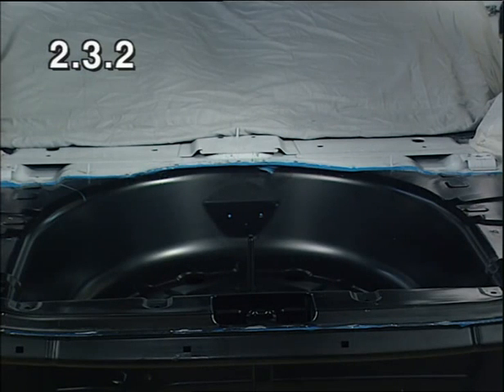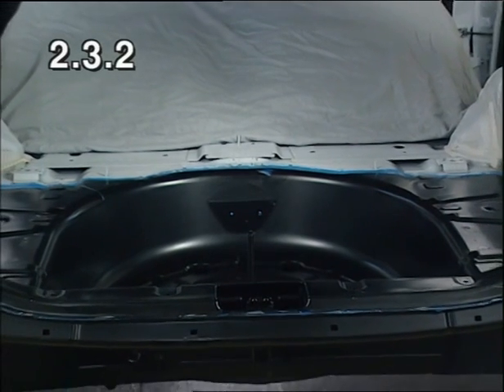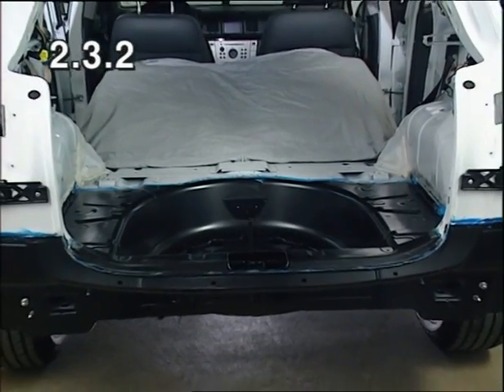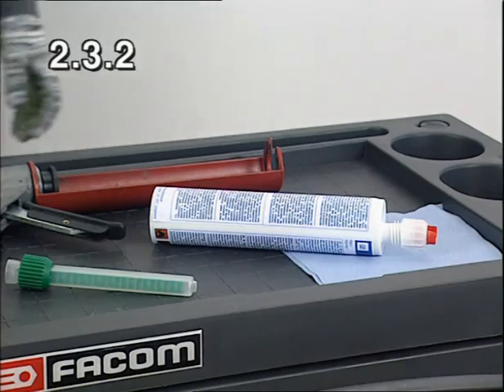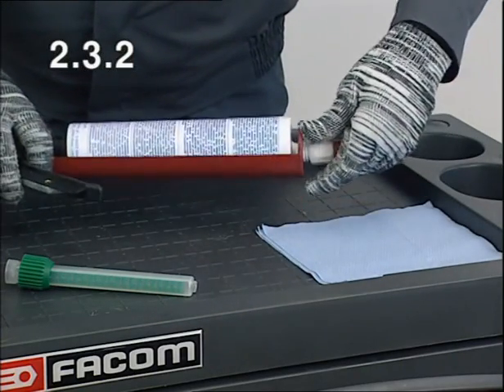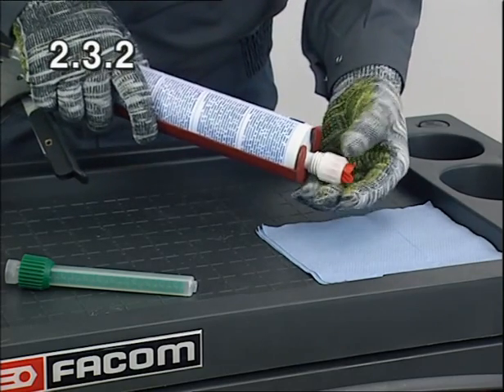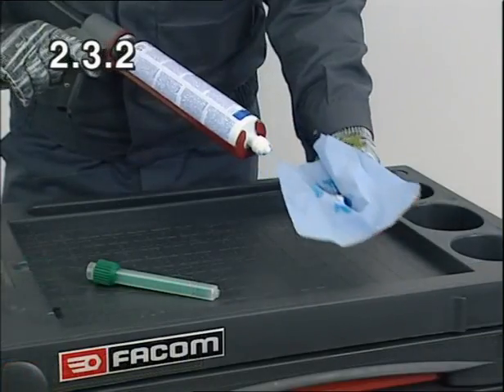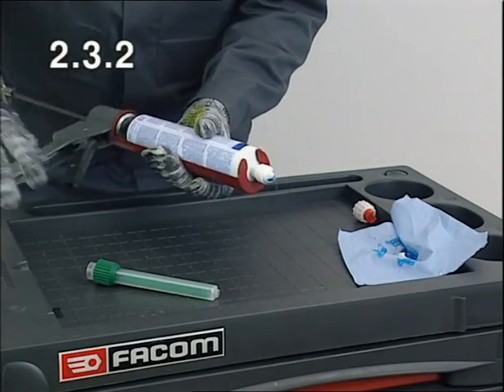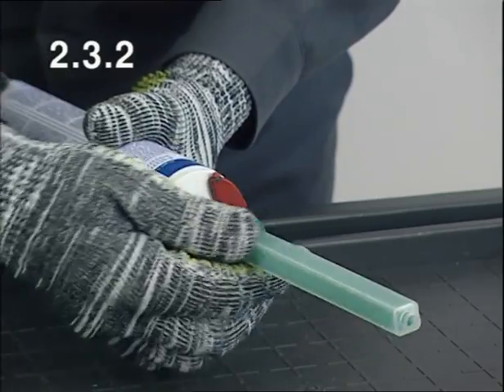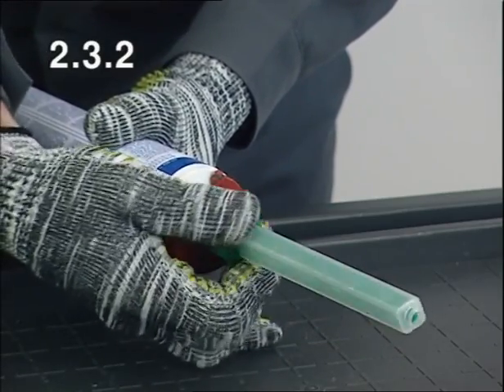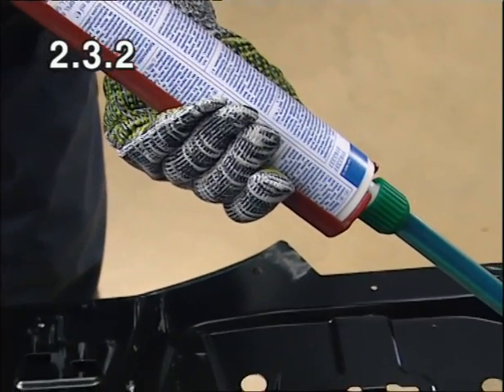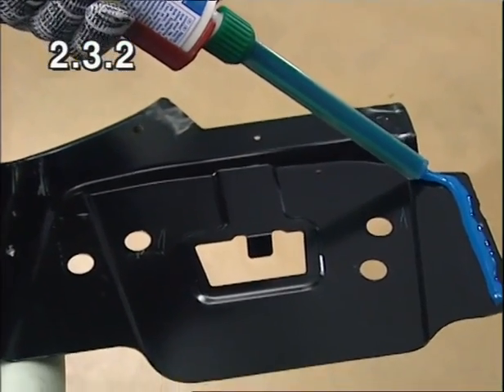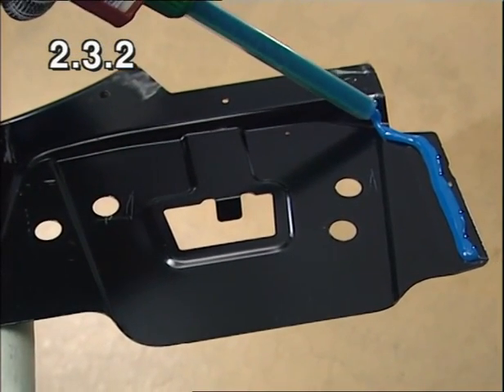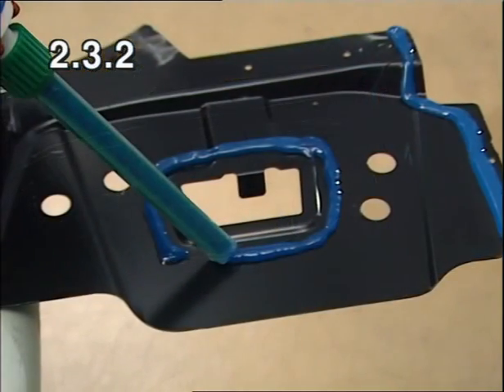The advantages of the increased handling time for the new two-component adhesive system are demonstrated using the example of repairing the rear floor and the lower rear panel with undamaged rear quarter panels. After inserting the cartridge, the two components are squeezed out until they reach the same level. Only then is the mixer screwed on, having been pre-cut to a 6mm discharge aperture. The adhesive is only applied to one side of the new component, the lower rear panel reinforcement, prepared in accordance with the service instructions because the assembly area contains multi-layer plates.